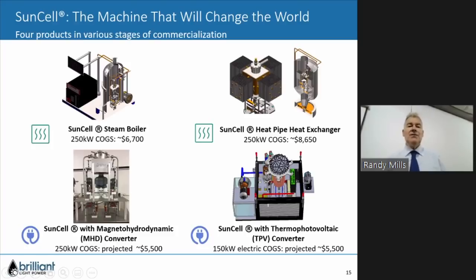And then the pressure in this reactor can be controlled by controlling the size of the aperture on the outlet of the steam boiler to create between half an atmosphere and 15 atmospheres, which is the standard pressures in commercially available boilers. In addition to the boiler, we have another type of heat exchanger, which involves heat pipes that are embedded in a series of thermal fins, and we blow atmospheric air through these fins that accept or transfer heat from the wall of the SunCell to these fins, and it heats up the hot air for variable temperature from 100 degrees C to 500 degrees C.